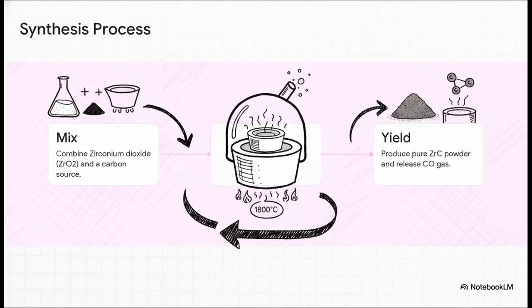Here's the foundational recipe to get that perfect powder, a process called carbothermal reduction. Basically, you mix zirconium dioxide with a carbon source, like carbon black, and bake it in a vacuum at a blistering 1800 degrees Celsius. The whole goal here is to release carbon monoxide gas and leave behind pure zirconium carbide.